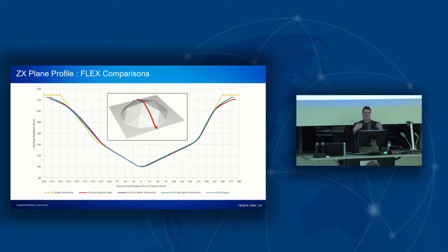So obviously, as I said, in this process, there's significant deviation of the sheet from the actual geometry you're trying to form, particularly in this sort of bending zone near the top, and then we get closer down the bottom. The simulations, however, very closely reflect what we're seeing in the scan profile, except perhaps in a region just up to the top right. I'm not 100% sure what went on there, but all other regions seem to be matching really well.